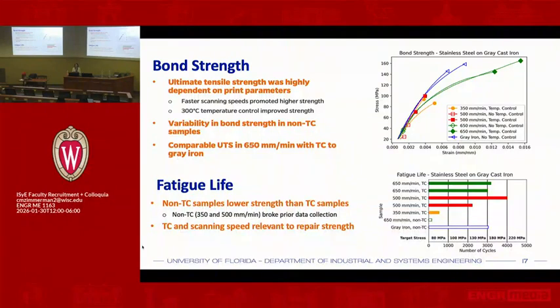In terms of the bond strength, a couple of things that you're going to be seeing here is that speed is going to be a major contributor for the integrity of that strength. And in terms of whether that particular heat treatment made a significant difference or not on the repair, nothing really large or nothing really conclusive came out of that aspect. Primarily it was the speed. Temperature control provided something, but not as much as we expected with the heat treatment operation. And so right now, of the different parameters that we were controlling, speed and power had a contribution in the bond strength and fatigue life of that repair.